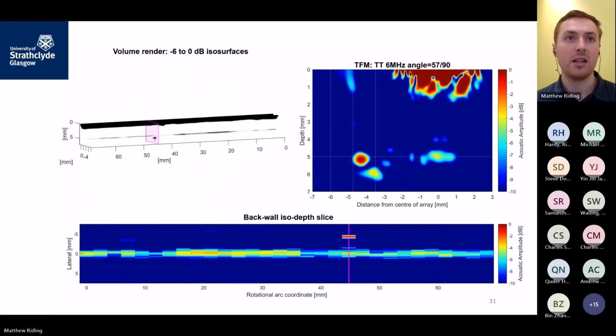There we go. The angle is plotted in the title of the image in the top right. And we've got this very strong indication at the backwall depth for an angle in that scan going from 0 to 90 of 57 degrees, and I was aiming for 60, so I clearly have a 3-degree positioning error in my hands. But we're pretty pleased that we've been able to detect it and that it's so clear.